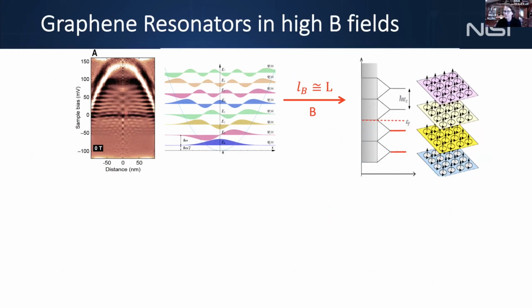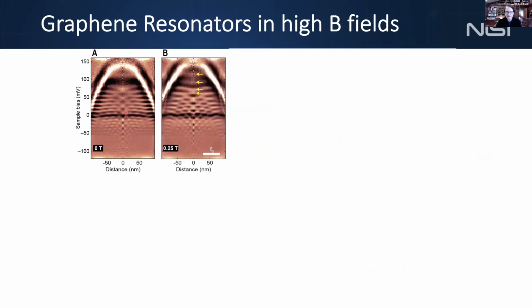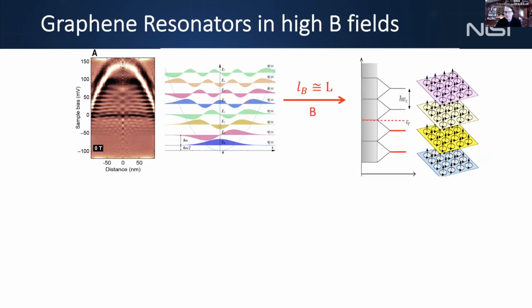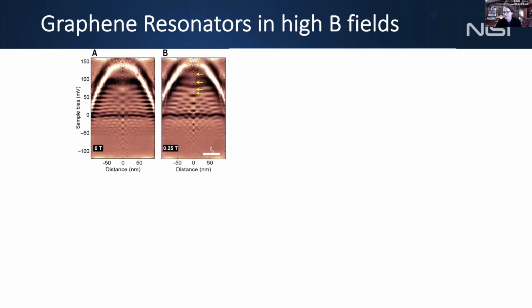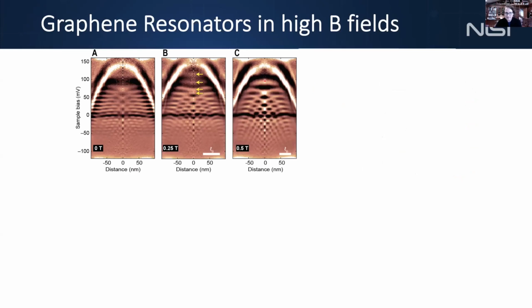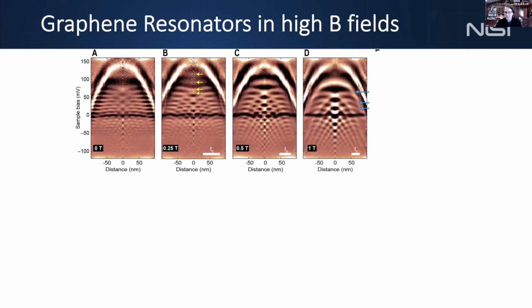So we'll simply take these maps now, and we'll vary the magnetic field. The field where we expect something to happen is when the magnetic length is on a characteristic scale here, which is on the order of maybe 50 nanometers. And that field scale should be on the order of 0.5 Tesla. So we should see something change on the order of 0.5 to 1 Tesla. At 1/4 Tesla, we just see the Berry phase doubling here. At 0.5 Tesla, we start to see some bright increase in density here at the center of the dot. And then that just gets more pronounced here at 1 Tesla.